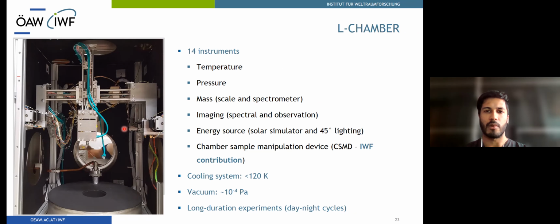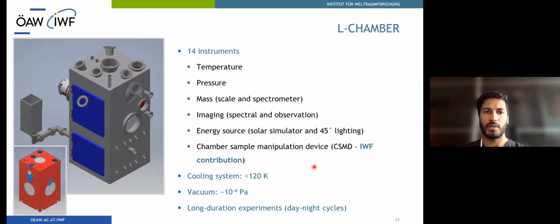The cooling system of the L chamber can achieve temperatures below 120 Kelvin, and a turbopump creates a vacuum of around 10⁻⁴ pascals. These conditions can be sustained over many days as the chamber was designed to simulate multiple day-night cycles.